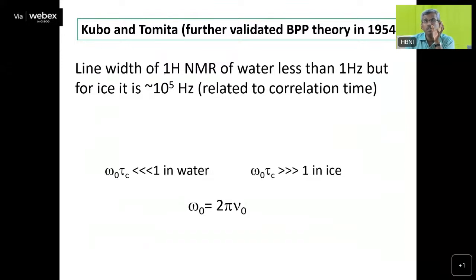But these explain qualitatively why the line width of solution NMR is much smaller than that of the solid. They demonstrated this with the help of H1 NMR of water as well as ice. Around 30 megahertz NMR they were doing, and they saw almost 10 raised to 5 times more line width when it becomes ice. This has been beautifully explained in terms of the correlation time.